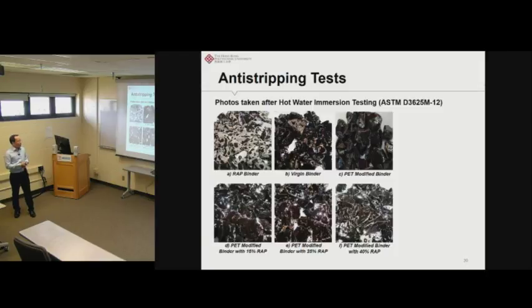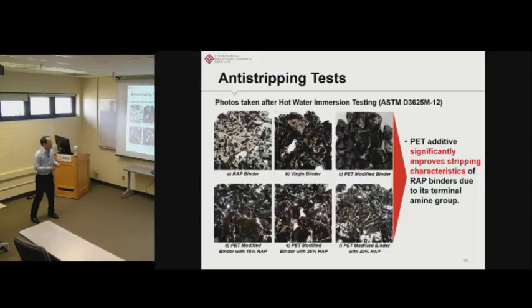And here, we can compare these pictures. So we can see even with the 40% of RAP binder, there's still a very good coating after the test, which is similar to the virgin binder, probably even better. But notice we have already added 40% of the aged RAP binder. So these tests are very promising, indicating that the PET derived additive seems to significantly improve the stripping characteristic of the RAP binders.